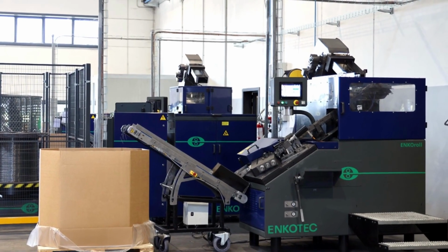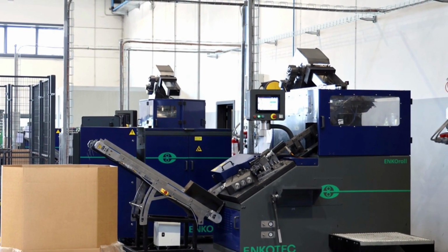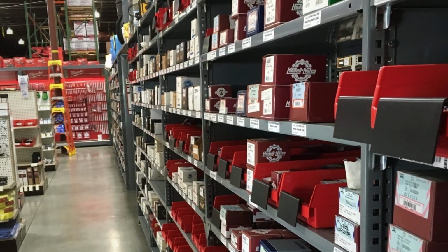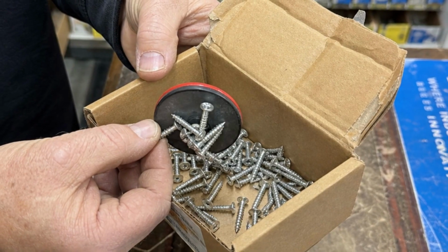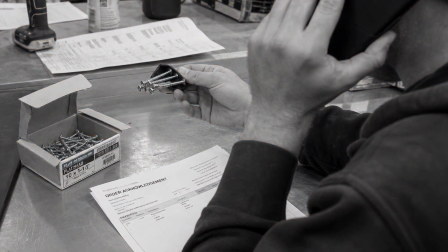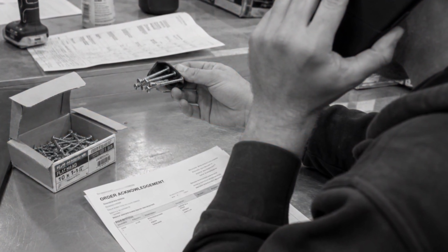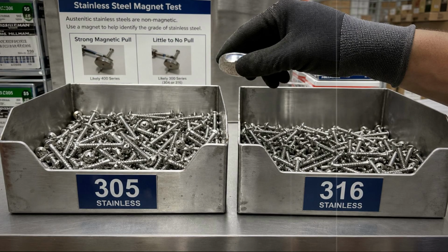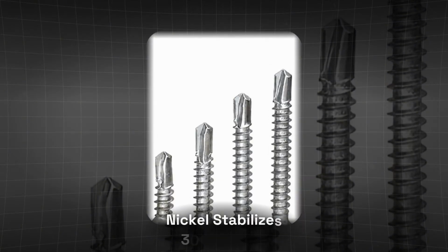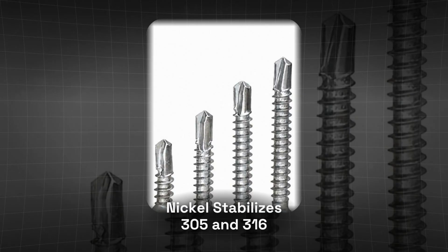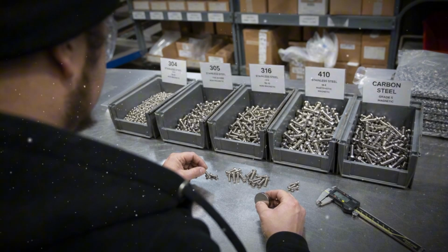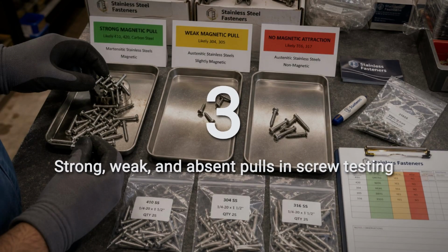The effect is strongest when cold forming smaller items, which means screws and nails specifically. Fastener distributors live with the consequences. A customer opens a box, jams a refrigerator magnet in, watches the screws stick, and calls convinced the order was wrong. Type 316 and Type 305 generally do not develop those magnetic properties because their higher nickel content holds the structure stable through forming.